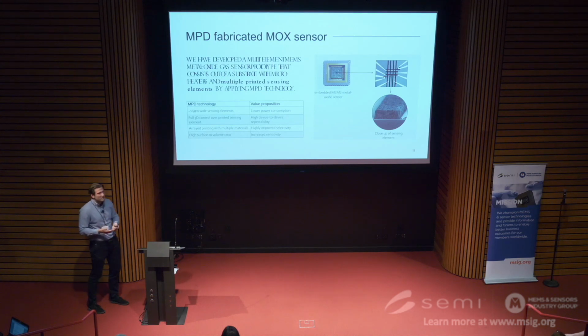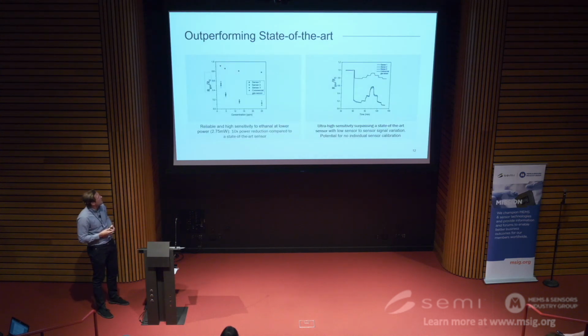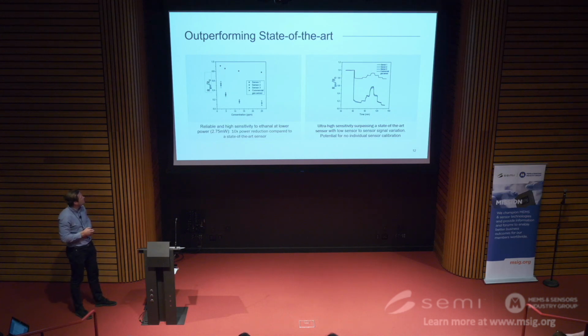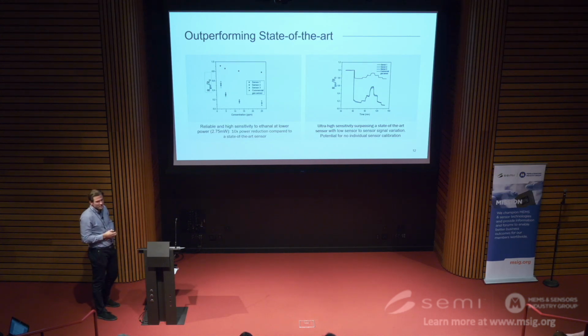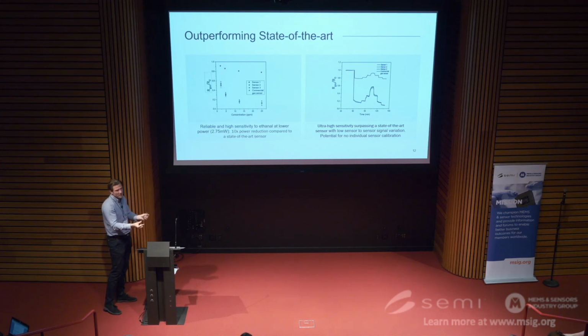Not only have we fabricated the device, we've also measured the device and compared it with a state-of-the-art gas sensor that we bought from Figaro. On the left, you can see sensor 1, sensor 2, sensor 3, which are three of our MPD-fabricated MOX sensors, compared to a commercial MOX sensor, which is the top line, basically the dots. From the data we see that we get a very high and reliable sensitivity, measured against ethanol. And we can also see that there's very little sensor-to-sensor variation. This is all due to the fact that the mold very well controls where the nanomaterial ends up and where it shouldn't end up.